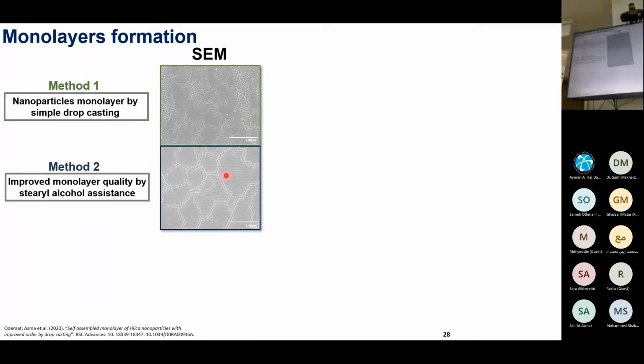Actually, the scenario behind the stearyl alcohol is not easy to explain, as it is complex. But as a speculation, maybe the precipitation of stearyl alcohol takes place on the particle or on the silicon wafer during the drying. Also, maybe the drying of the edge of the droplet plays a major role in improving the ordering between the nanoparticles in the monolayer formation. This is only a speculation, as the description of monolayer formation is not an easy issue.